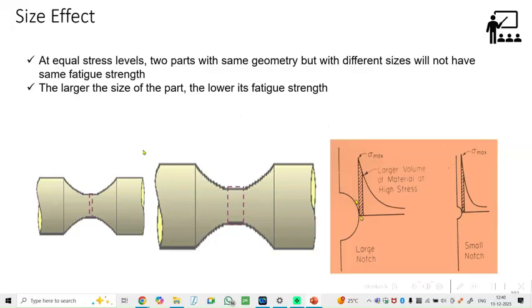Residual stress aspect, obviously we have seen that any process that induces tensile residual stress is detrimental. I don't know whether you are aware that sometimes when a small component is machined, they put it on a vibration table, because the process of machining induces tensile stress. The purpose of vibrating it at high frequencies is to relieve those residual stresses. That's one of the processes they do.